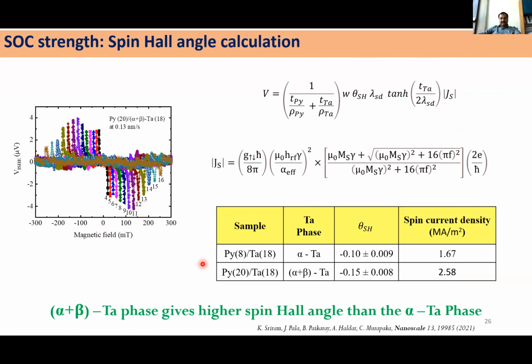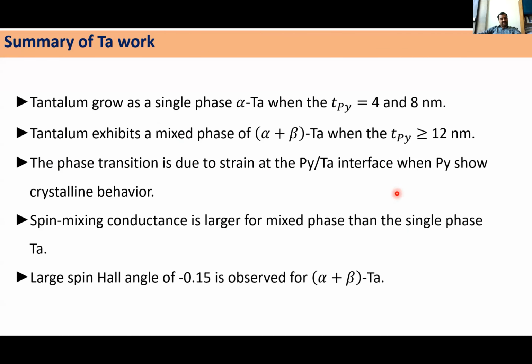Okay, and from there, by using this inverse spin Hall effect, we found that the spin Hall angle in the alpha plus beta, that is the mixed phase, is 0.15 as compared to the single phase alpha. So it shows that the mixed phase can give us a higher spin Hall angle as compared to the single phase alpha. So just to quickly conclude the tantalum work, tantalum grows as a single phase when we grow on